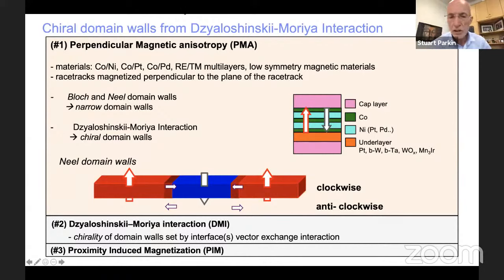Most importantly, it gives rise to something called the Dzyaloshinskii-Moriya exchange interaction, which means that through spin-orbit coupling, for example, in this cartoon, the dark green layer, which is a cobalt layer, sitting on top of the underlayer, let's say platinum, cobalt moments interact and are exchange coupled through platinum. And because of this spin-orbit coupling phenomenon, the broken symmetry, it leads to an exchange interaction where the magnetic moments in the cobalt layer want to be aligned, not parallel to one another, but perpendicular to one another. Moreover, they're aligned in a vector fashion. So the Dzyaloshinskii-Moriya exchange is a vector exchange, which means that the moments want to be not only perpendicular, but they want to be clockwise or anti-clockwise oriented, as shown in this cartoon.